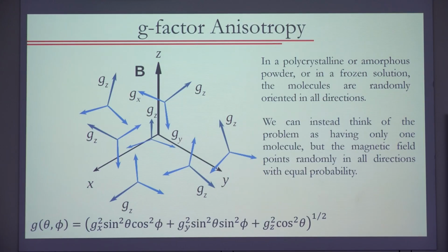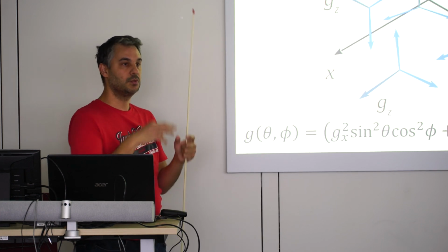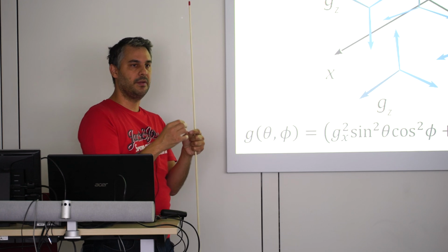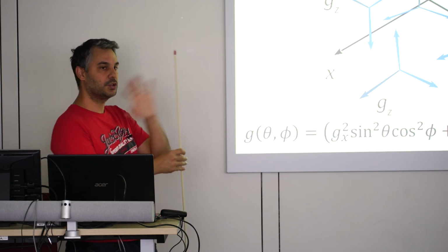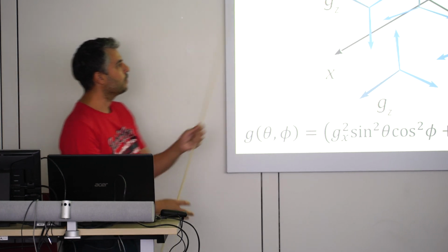But why am I measuring this? Let's say you have a powder. You don't have a single crystal, you have a powder that's like ground single crystals. You should always grind single crystals if you can. Don't use a powder directly from a precipitation, because it may have some small crystals and not so small, and then it's not completely random. It's better to grind it before doing this.